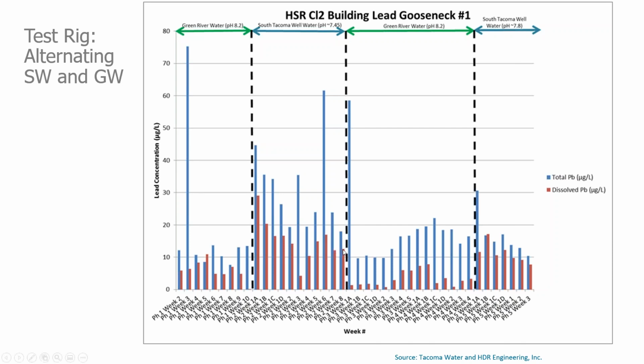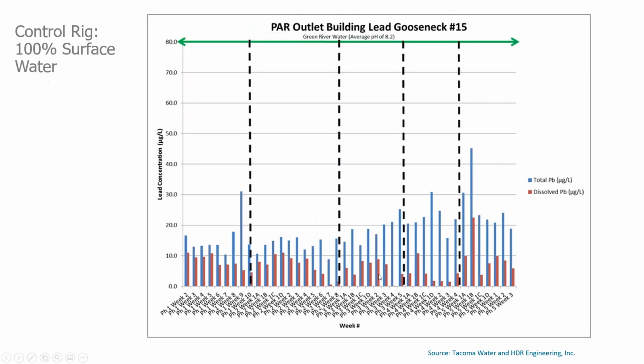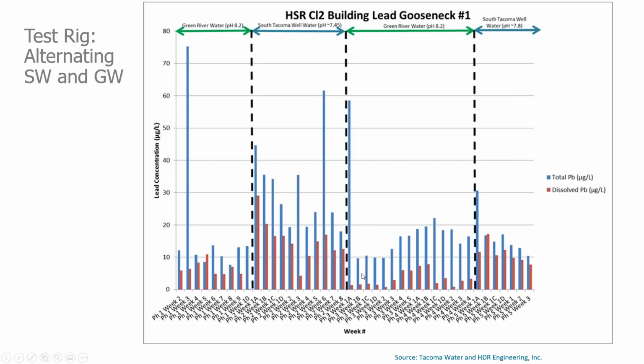And we see that it finally does settle down when we switched back to the surface water, and we get a very big particulate lead release at that time, because again, we've got to change crystalline structure. Can't really explain why dissolved lead was so low here. We did see lower dissolved lead in the control at that time too, but still more particulate than when we started. And then when we switched back to groundwater, again, a big particulate release and slightly lower dissolved lead at pH 7.8. This is again the higher pH groundwater, slightly better than what we saw at pH 7.4. So we see the actual results of these changes going from groundwater to surface water, particulate release, and scale predicted to be due to changes in the mineral structures.